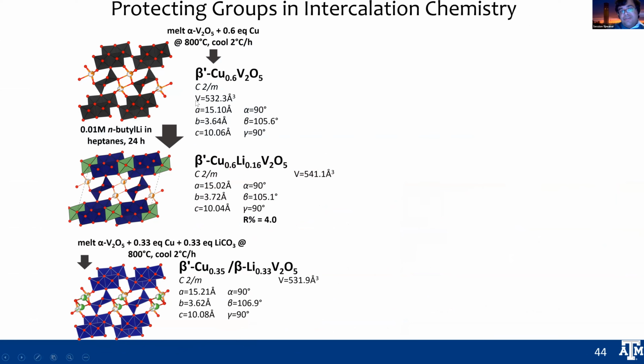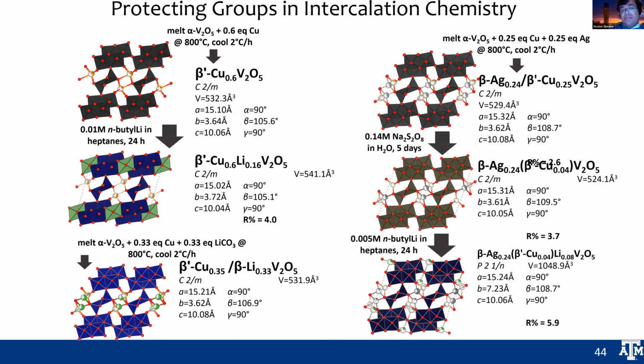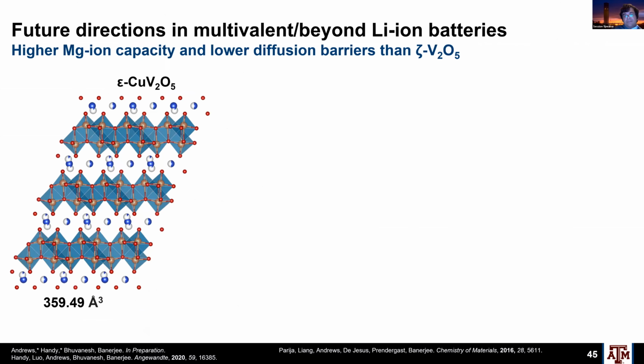Okay, and another cool thing that Joseph has been doing is the idea of protecting groups in intercalation chemistry. Because we can work with single crystals, if you've got a little bit of copper in there, or a little bit of silver in there, where does the lithium then go? If you end up blocking some of the sites in the tunnel, could you direct the lithium ions down specific routes? This has been very exciting because we can specifically position lithium ions in about 4 sites, depending on what else is present.